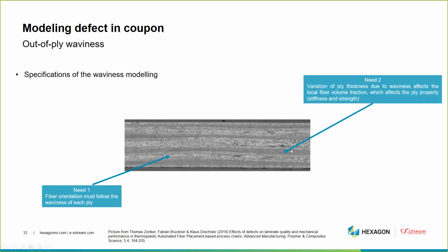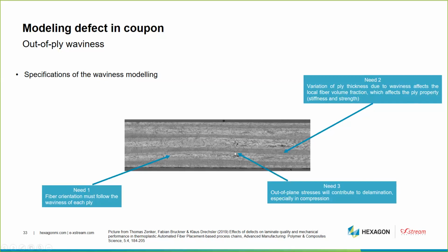We can also observe some large variation of the ply thickness due to the waviness. So it means that if we have variation of the ply thickness, we have a variation of the local fiber volume fraction, which probably will affect the local ply, in terms of stiffness and strength. We have also probably apparition of the out-of-plane stresses that will contribute to the delamination, especially in compression. And we see also that we can have several wavy areas over the coupon with different types of curvature.